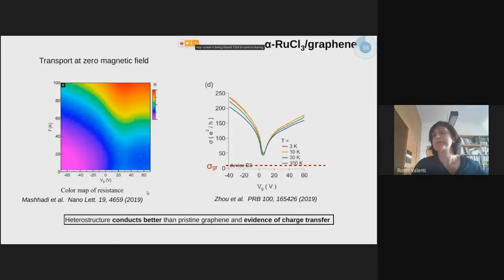And what is interesting about this heterostructure is the following. In these experimental realizations, what they find, first of all, is that there is an increase of the conduction in this heterostructure compared to what you expect for graphene. So that means that there must be a charge transfer between these two layers. And this is the simulations that we did. So Sananda Biswas in Frankfurt did these simulations, where by using DFT, what one observes is that two things happen. One is that there is a charge transfer from the graphene to the ruthenium trichloride, so that's why the system becomes more conductive, because there are more holes, more charges in the system.